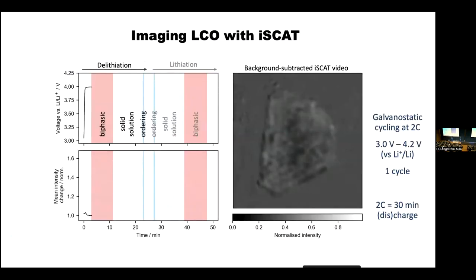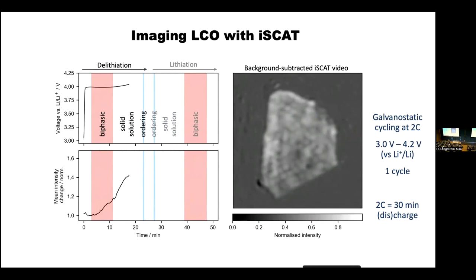So let's now look at this image that we collected just before lockdown in 2020. So this is the first iSCAT image showing you the solid solution regime. Watch out now, because you can see the ordering transition at Li 0.5. You'll see it whipping through the sample here. And then we come back, there's the ordering transition again, the solid solution. It's becoming darker as you're pulling lithiums out and the scattering is changing. And then you're going to see this two-phase reaction.